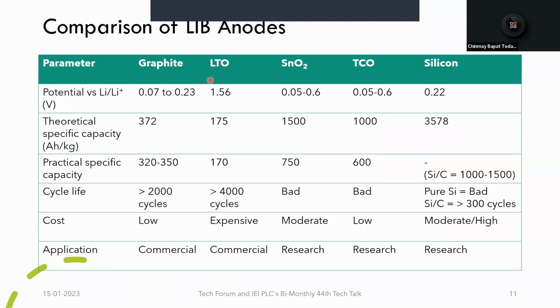When we look at the comparison of the different anode materials, we see that graphite has a moderate specific capacity. Lithium titanate has a low specific capacity, but a much better cycle life and stability. And therefore, it has been commercialized, but to a lower extent because of its low specific capacity. Tin oxides and tin composite oxides have very high specific capacities, but their stability and efficiencies are low, and therefore the cycle life is much lower, and therefore they're only in the research stage.